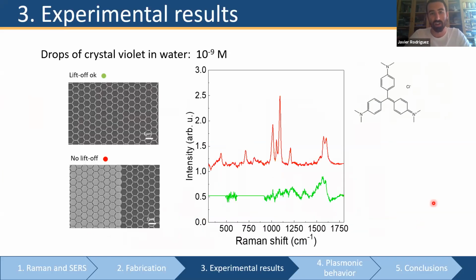So as I was saying, if you take another design, for instance, this honeycomb lattice that you have already been introduced to, you see again the same results, with the difference that this time the drop that was cast was of a concentration of 10 to the minus 9 molar, which was something very remarkable for us, because this is again a very simple experiment to conduct, because it's just taking a drop of the solution that we are analyzing and casting it on top of the surface, waiting for 2-3 minutes for it to dry, and then performing the Raman spectrum.